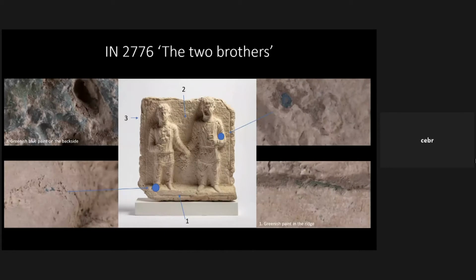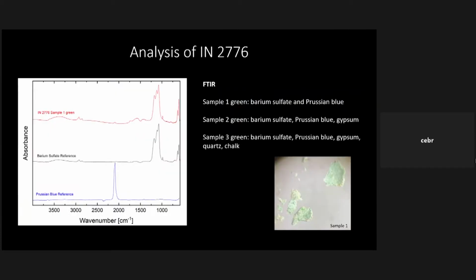This relief has several traces of green and blue paint distributed over the surface. Examples of paint traces are indicated on the slide, but many more were detected by visual inspection and microscopy. It was examined with VIL, which showed no indication of Egyptian blue. 3 samples from the greenish paint traces were taken and examined by FTIR in September this year. This showed that sample 1 of the greenish paint contained barium sulfate and Prussian blue. Sample 2 contained barium sulfate, Prussian blue, and gypsum. Sample 3 contained barium sulfate, Prussian blue, gypsum, quartz, and chalk.